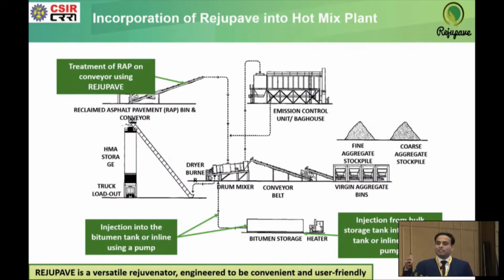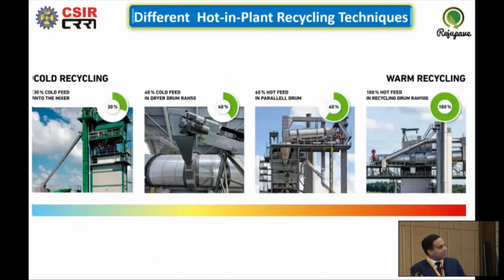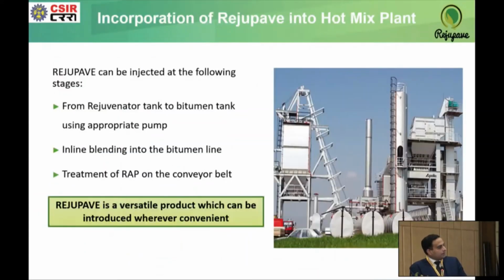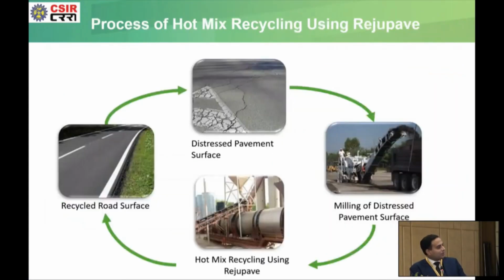Now where can we put this RejuPave rejuvenator? It can be added into the virgin bitumen tank at the requisite dose. The dose is around 0.5 to 1% by weight of virgin binder, so that too is quite economical in nature. Or it can be directly sprinkled on the oxidized RAP inside the pug mill. So these are the 2 ways we can put the RAP rejuvenator inside it. So it's a glimpse of a hot mix plant where we can do all these things.